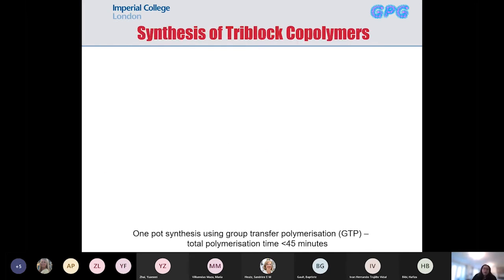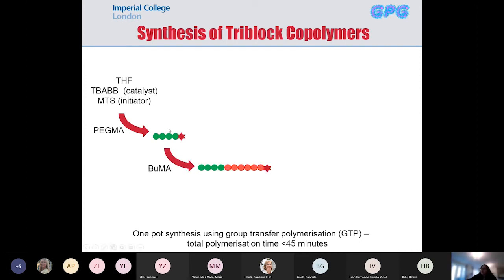All this was done with group transfer polymerization, the polymerization method that allows us to synthesize methacrylates at very high scale. So it's very easy to scale it up. And it's also quite a fast polymerization method. So each step is about 15 minutes. So you have your solvent, the catalyst, and the initiator, and then you add the first monomer to produce the first homopolymer. Now it's a living polymerization technique. That means this active group will still remain living, alive, if you wish. So it will still stay active.